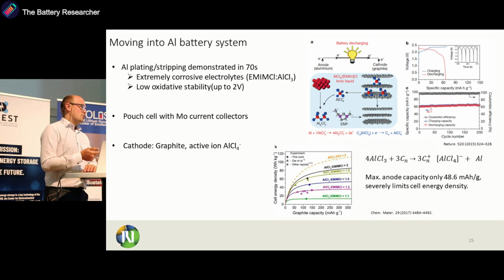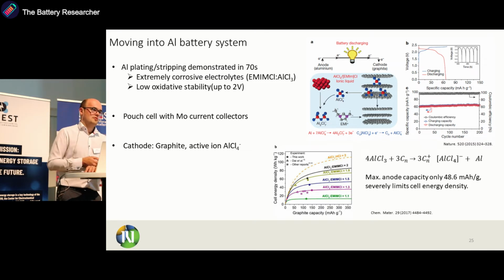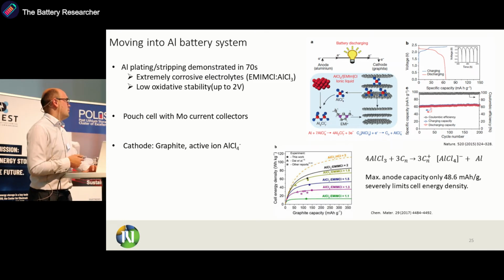So this has really important implication because actually aluminum metal anode is not the anode in this system. The anolyte is basically aluminum chloride, which is here inside the electrolyte, and basically we need quite a lot of it to form these ions, and this limits our anode capacity to only 50 milliamps per gram. So this is a huge decrease from almost 3,000 milliamps per gram of aluminum metal anode to only 50 milliamps